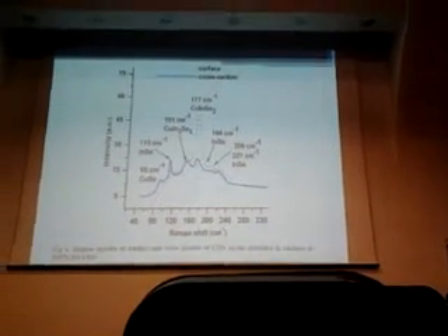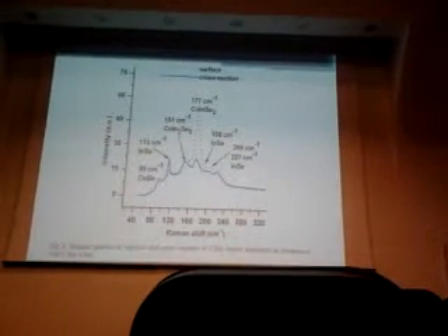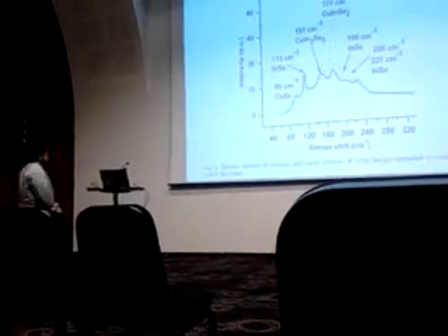This is the concluding graph of the Raman spectrum with surface and cross section. At the surface, copper indium diselenide is the dominating phase, while in the cross section, copper indium 3 selenium 5 is also one of the prominent phases along with copper indium diselenide phases.